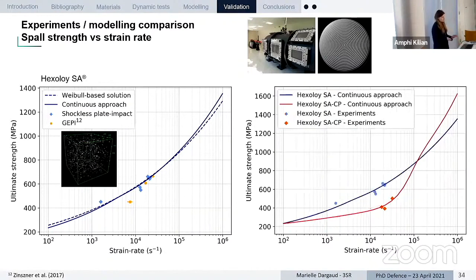When we compare the two materials, we can see that in the end, the very high increase of strength sensitivity above a certain threshold for the Hexoloy SA-CP leads to, in the end, reaching a higher level of strength compared to the other material which did not have these large spherical pores.